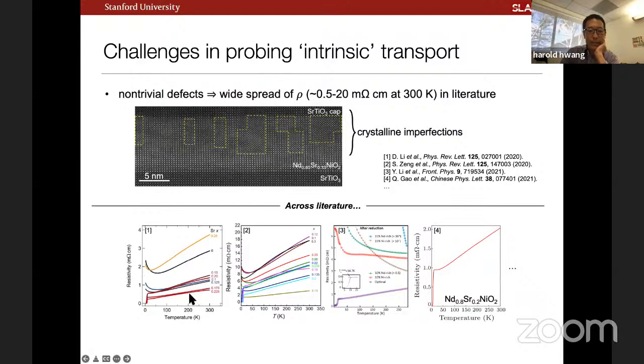And what you can see is that this is our work, various versions. You can see that the scale of the resistivity is kind of varying by a factor of 40 or so. And even in our own work, we can find that there's quite a bit of order factor 2 variation sample to sample that we think are arising from these extended defects. Okay. So what are they?